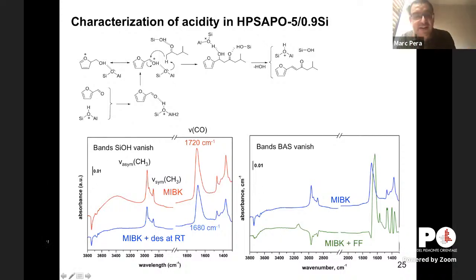This information came by analysis of in situ infrared, using MIBK, by adsorbing MIBK, desorbing at different temperatures, and also desorbing MIBK and adsorbing later furfural. I'm not going to enter into detail, but we see some shift of the CO stretching of MIBK, that is interaction with silanol. Some bands here that disappear or don't disappear. So from all these analyses, we can get all this information.